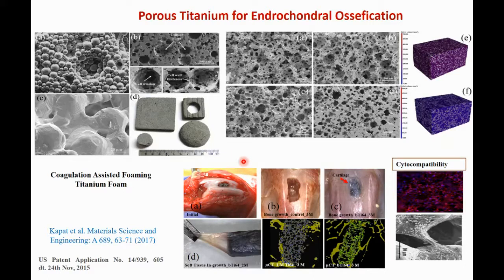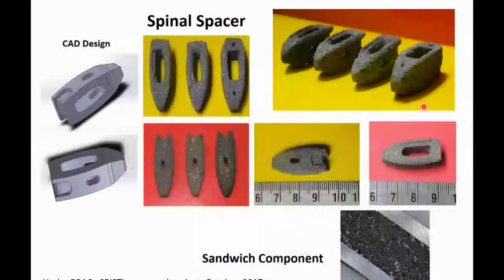We have done a series of products, and as you can see from microCT results, we are able to make porous samples whose porosity can be varied from 45% to 90%. So we have made a series of spinal spacers, and this spinal spacer design was borrowed from Zimmer, and this project was done under the Bioactive Srishti sponsored project. And we have shown that using this porous titanium, we can make the spinal spacer. Currently these porous titanium spacers are marketed by Zimmer and some other companies. But in India, there is no such indigenous company making porous titanium.